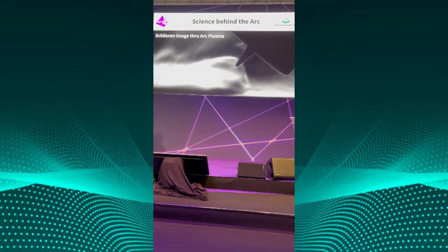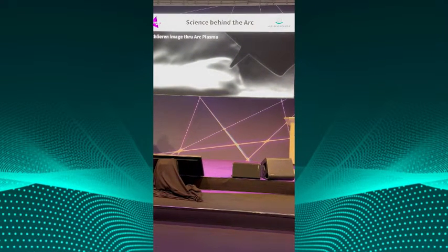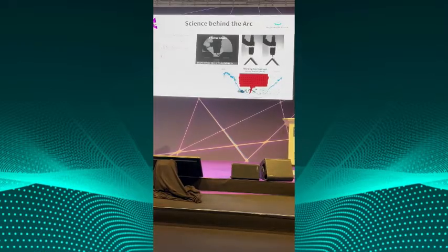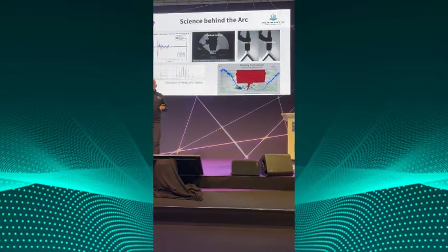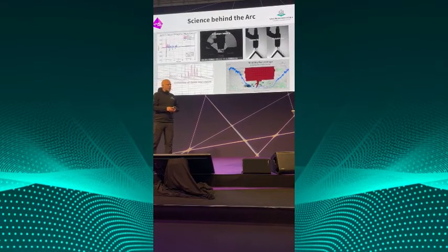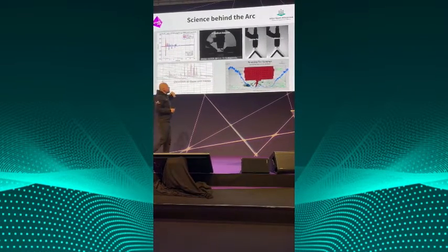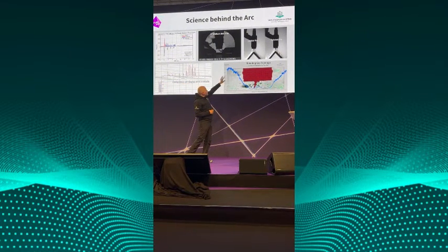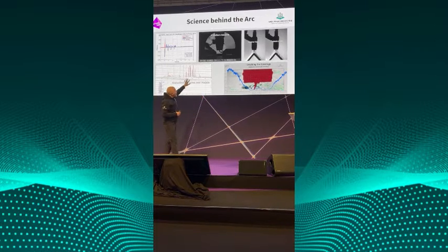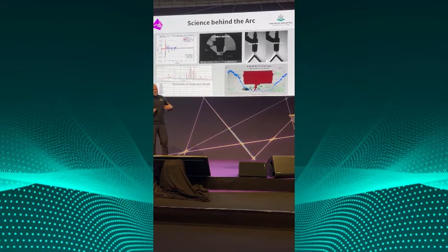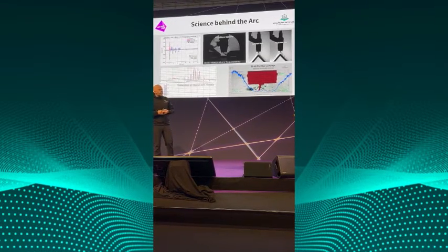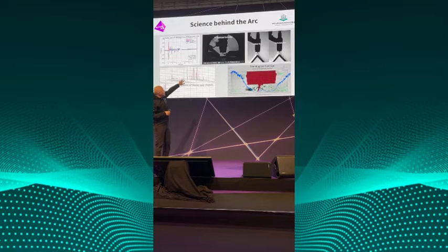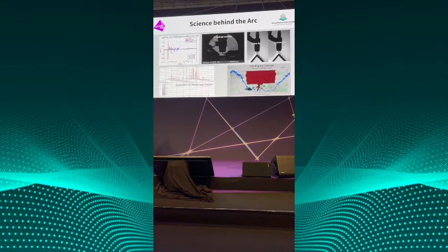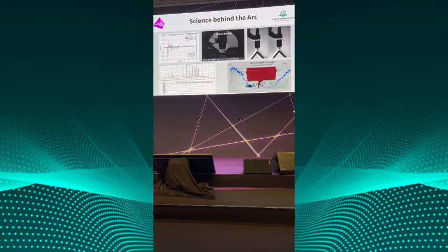So this is a Schlieren image. This is a special optic technique. What we actually see is kind of an X-ray of the arc. So we see the outline of the arc and the very high temperature, but also the tungsten. And this is something I would encourage people to see: there is a science behind welding. So today we have methods such as Schlieren imaging to quantify if a shielding gas flow is turbulent or laminar. We have high fidelity and high acquisition rate or frame rate imaging techniques where we can analyze in situ how the gas is flowing and how you can increase the protection of the shielding gas.